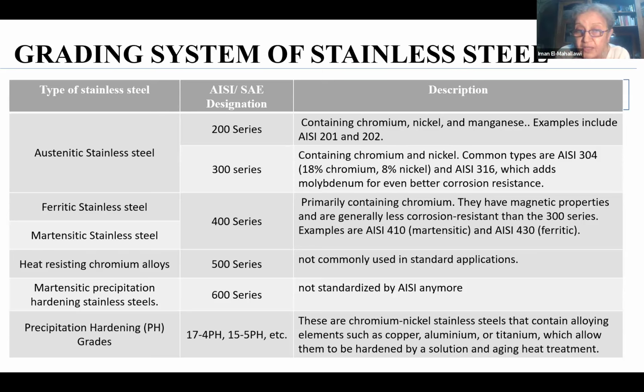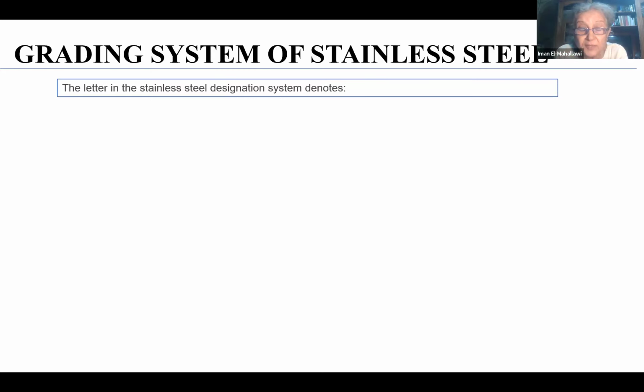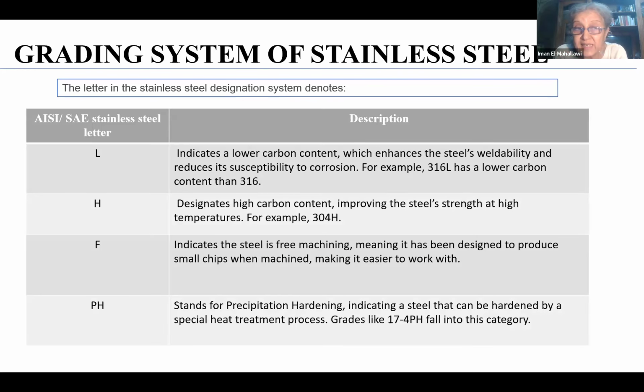So when we need higher strength and maybe different corrosion conditions, we can use them. We have also the heat-resisting chromium alloys for high-temperature applications, martensitic precipitation stainless steels, the 600 group, the precipitation hardening groups, and the duplex stainless steels as well. All these are different alloy steels. In stainless steels, we should not forget that we have another suffix at the end of the number, which is L, H, F and PH. For example, the L would be extra low carbon, the H would be high carbon content, the F indicates the steel is free machining, and the PH stands for the precipitation hardening groups.